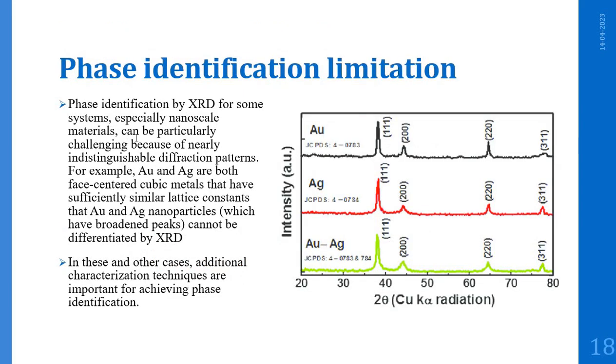Phase identification by XRD for some systems, especially nanoscale materials, can be particularly challenging because of nearly indistinguishable diffraction patterns. For example, gold and silver are both face-centered cubic metals that have sufficiently similar lattice constants, say gold and silver nanoparticles. In this case, it is very difficult to distinguish between these two metals. You can see from this figure that the graph shows peaks which are almost similar for gold and silver because of this face-centered cubic structure. If you mix both, you will also get the same peaks, so it is very difficult to differentiate between these two metals. In these and other cases, additional characterization techniques are important for achieving phase identification.